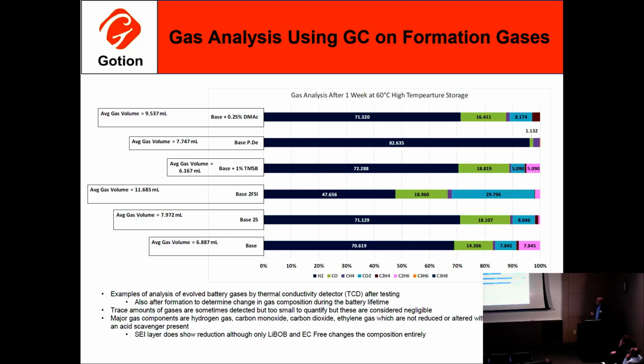But we also look at the gas that's formed, because that's critical: the dark bars are hydrogen. Obviously electrolyte's flammable, so you're producing a flammable gas. If you're worried about safety concerns like we always are, then obviously you're compounding problems, so you want to minimize that. You can look at this case here, where we've taken the ratio of hydrogen from almost 95% in this particular electrolyte case and reduced it to less than 50%. So it takes a lot of tweaking and analyzing, but the idea is really, where do the additives go in the electrolyte? What do they do? What gases are formed, and are they reacting at the anode or at the cathode? We're trying to understand that.